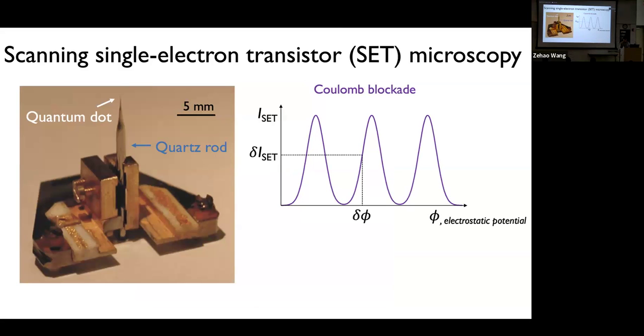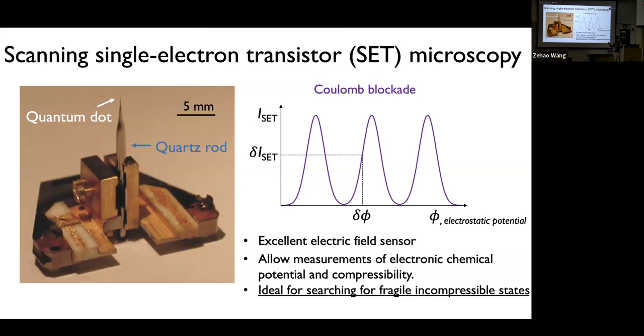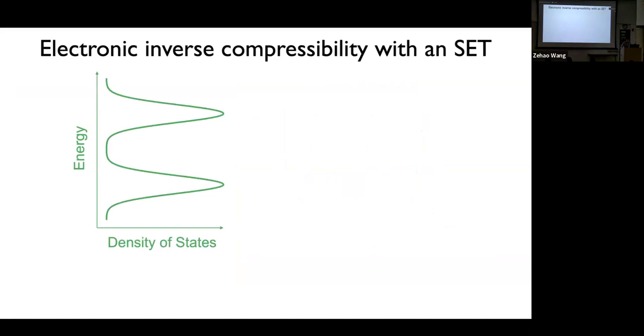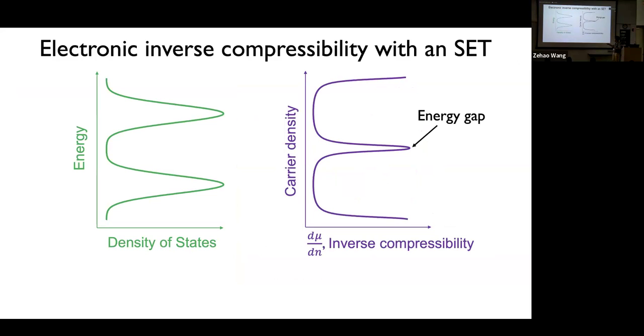In practice, you see that if you are able to place yourself here, any small change of external electric field would cause a pretty large change in the SET current. That means this is a very good electric field sensor, and you can use it to measure electronic compressibility and also detect incompressible states. Just as an exercise, if you have a system described by this kind of density of states with an energy gap, what you will measure in electronic compressibility, usually with the x-axis being carrier density, is a spike, because the system is not compressible. And it's very similar to the capacitance measurement that I introduced to you.